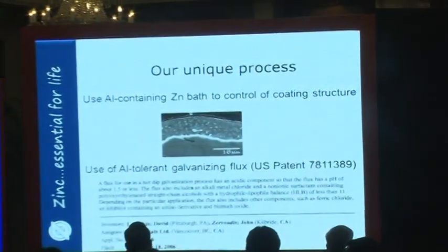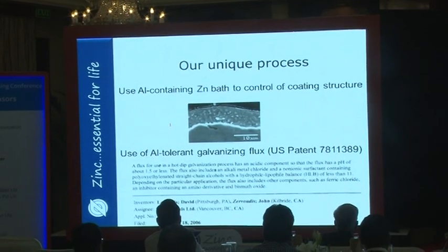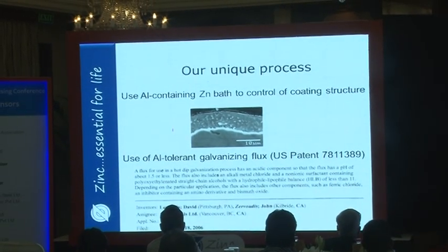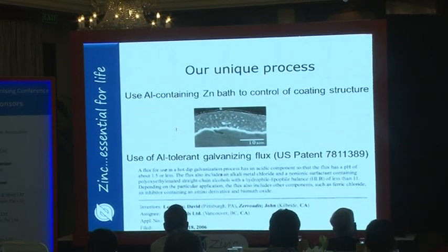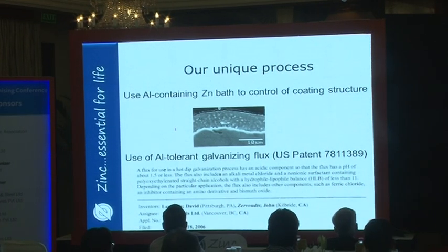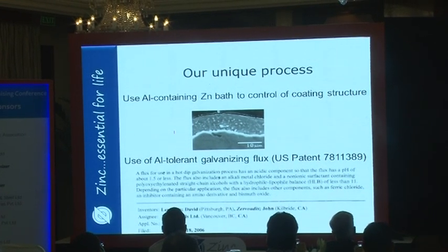So this uses a zinc 0.2 to 0.4% aluminum. We like using the lower end of it. We like 0.2 aluminum because it's got a higher viscosity, which is allowing us to have a higher coating thickness. And this produces an iron aluminide layer, Fe2Al5, rather than the iron zinc. We don't have the zeta, delta, gamma as you do in the regular pure zinc galvanizing. We have the iron aluminide.